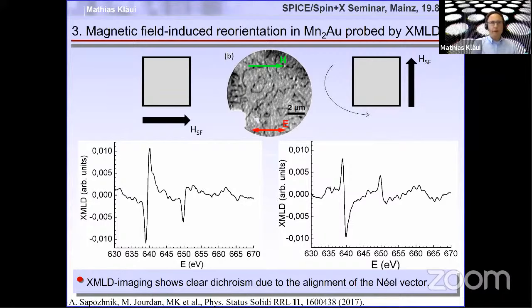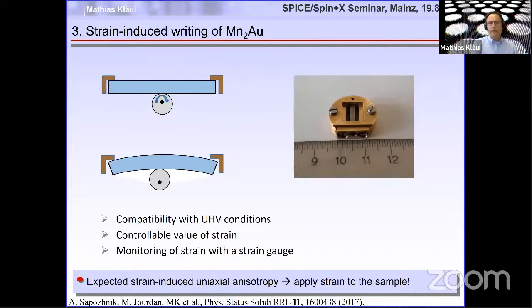Now, an alternative approach is to actually use strain. So strain can also induce anisotropies. And therefore, by applying a strain, we can orient the Néel vector in a direction set by the anisotropy due to magnetoelastic coupling, which many of these antiferromagnets have. So this is the strain gauge, which looks a little bit like a medieval torture instrument. We can put the sample on it, torture it a bit, until it breaks.